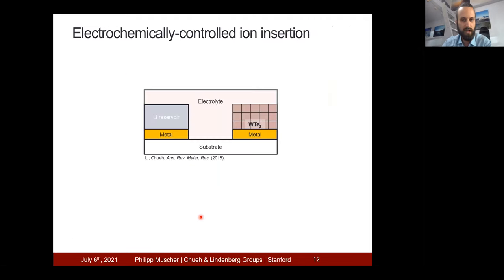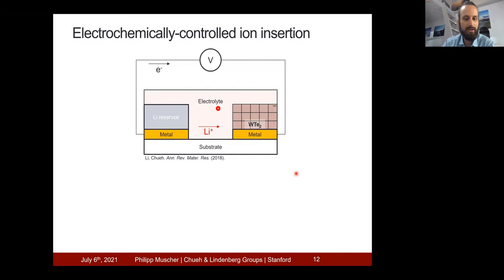So our platform consists of two electrodes, one of which is the lithium reservoir, and the other one is our material tungsten ditelluride. And in between, we have an electrolyte which only conducts lithium ions and no electrons. And we can use an external electrical circuit to control that an electron moves over from the left side to the right side. And now we have a negative charge over here, which drives ionic motion. So a lithium ion will now follow from left to right. And we can count how many electrons we're sending through the external circuit. And from this, we can deduce exactly how many ions we have inserted into our material.